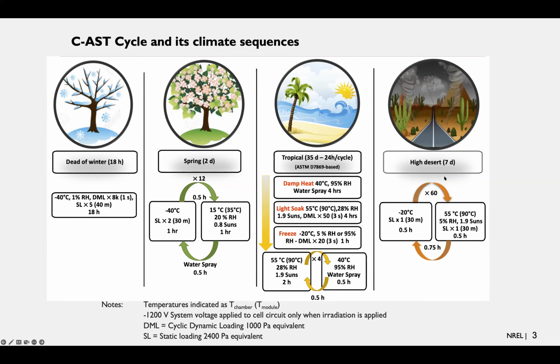And then finally, there's a high desert sequence, which is in the dry. We maintain the relative humidity very low, and we're cycling with light between -20 degrees C and 55 degrees C air temperature, and the modules get up to 90 degrees C. And that's true in these two sequences here. The module sees a maximum of 90 degrees C, and that replicates the highest temperatures that modules get to on a close mount roof in, say, Arizona, or a building integrated product where the back doesn't have free airflow. So that's the philosophy of the combined accelerated stress testing, and these are the cycles that we applied in the tests here.